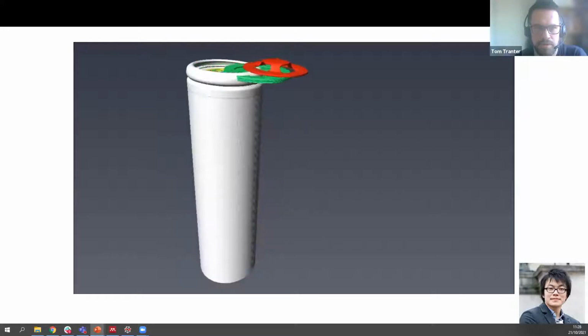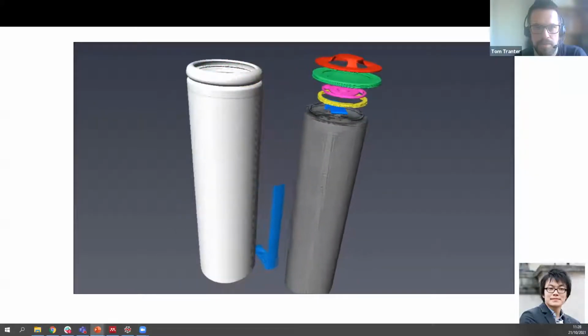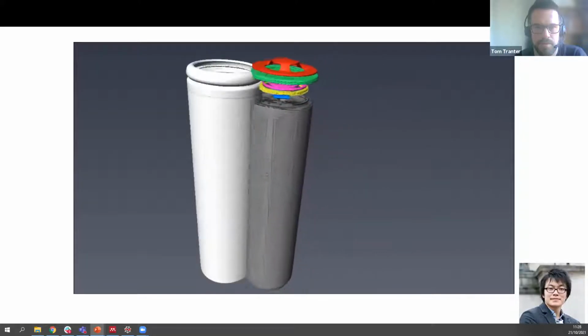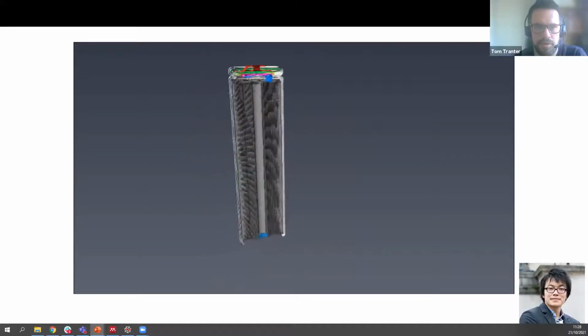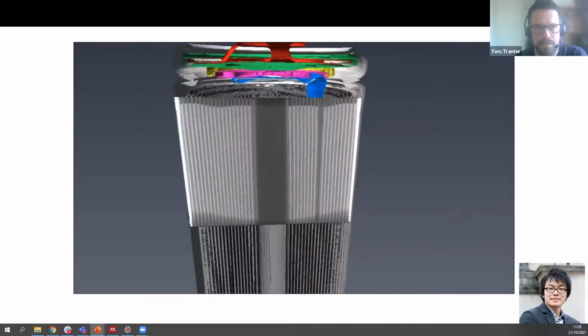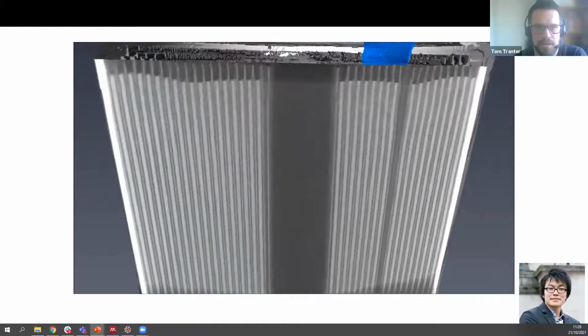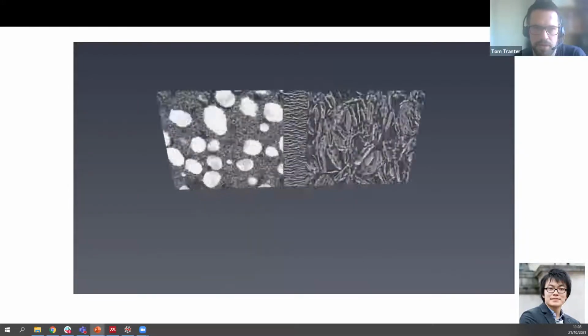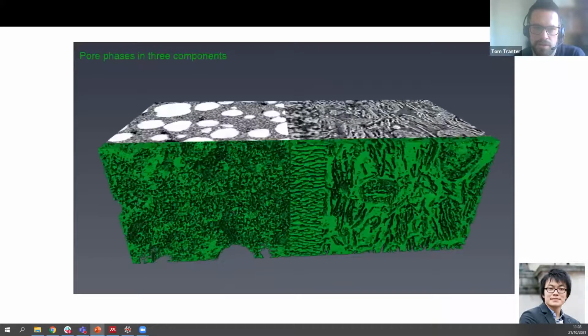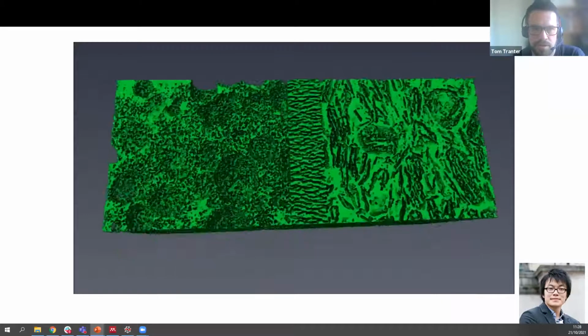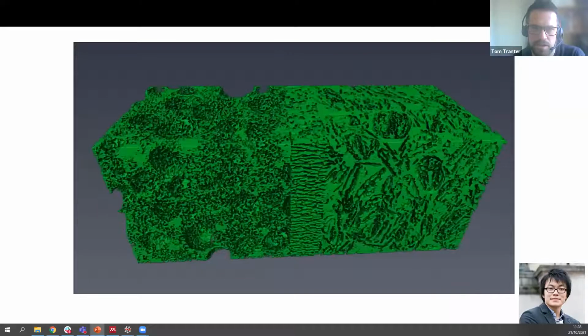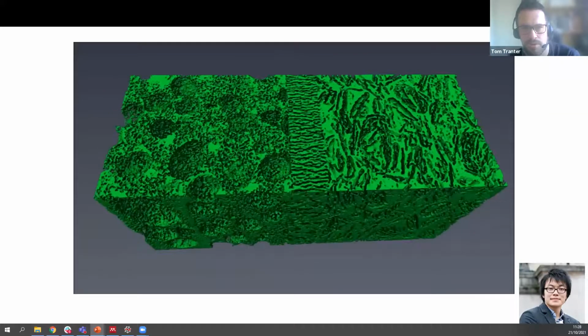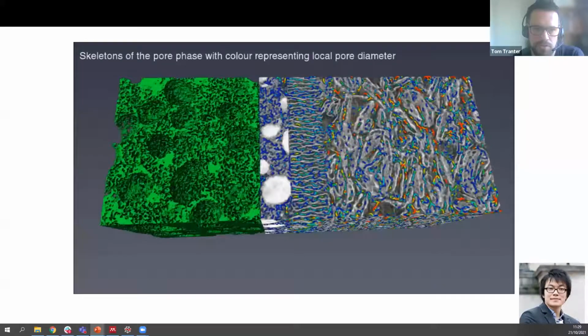So here we have the whole cell being scanned, the different components. And then we can zoom in and we can see all of the layers. On the left, you have the cathode, in the middle, the separator, and on the right, the anode. Once we have the image, we threshold it to resolve the different phases. And here you can see the solid phase. And you can see that each one of these materials is a porous material, which would be filled with electrolyte, where the ions are transported.